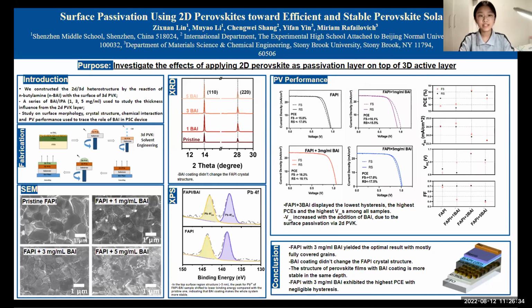Our XPS test showed that at the top surface region of the perovskite film, which was around 5 nanometers, the peak corresponding to lead ions in the 3 passivated samples shifted to lower binding energies compared with the pristine sample, indicating that 2D passivation made the whole system more stable.